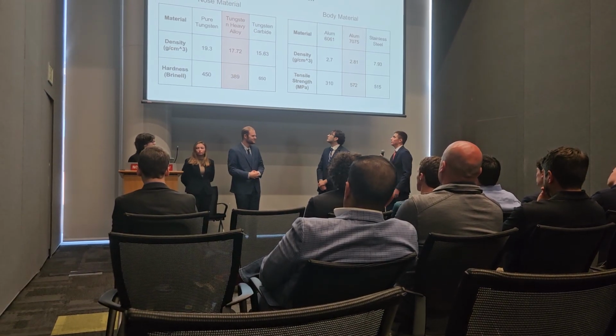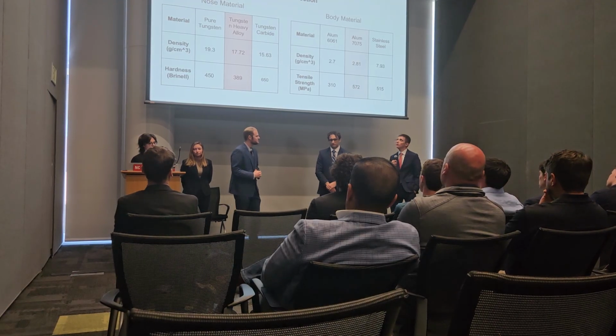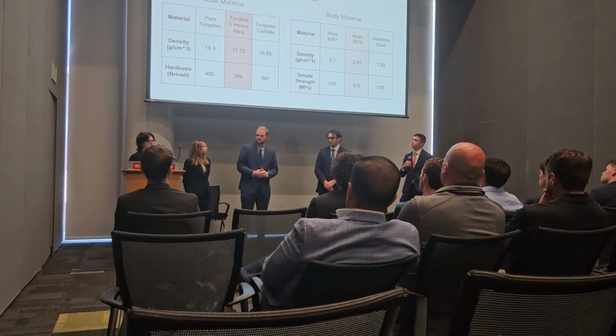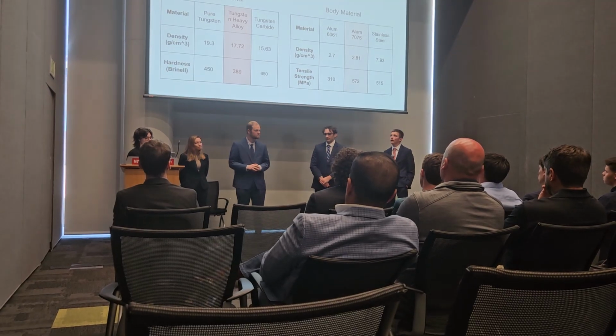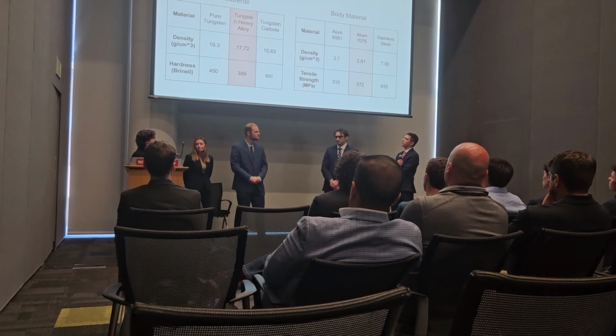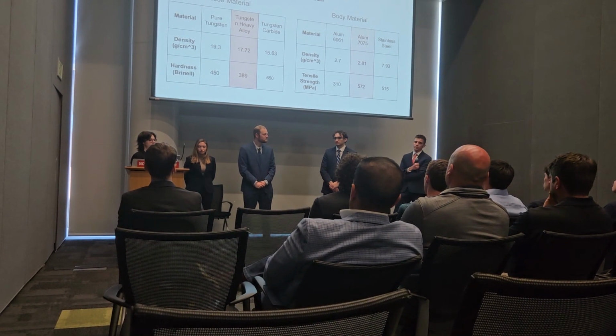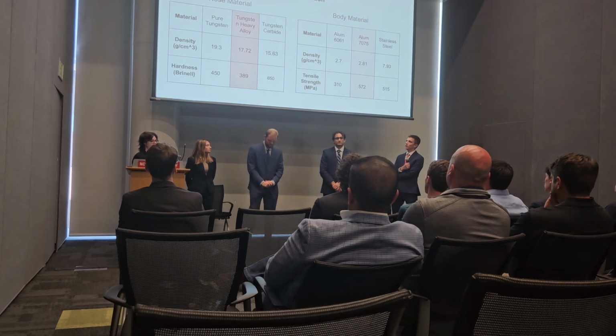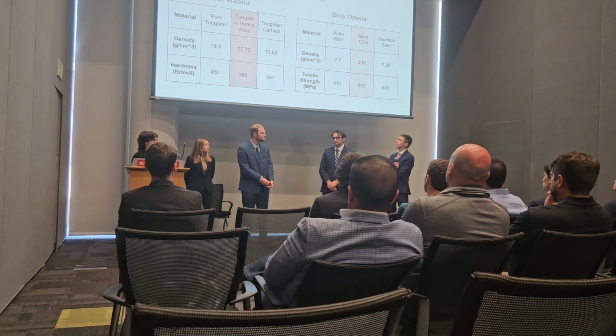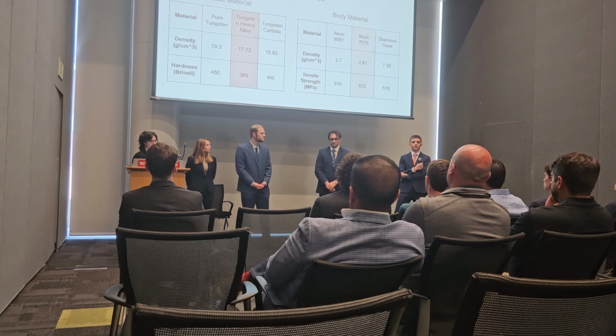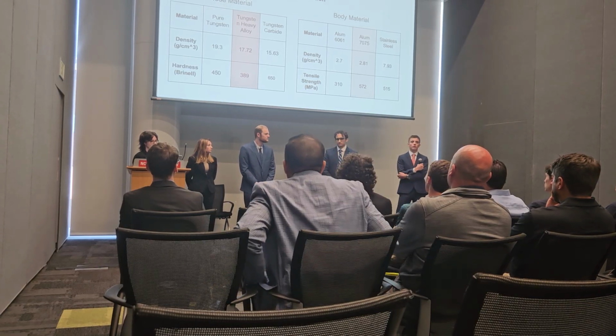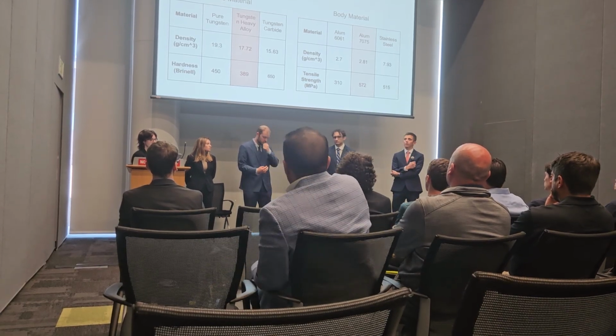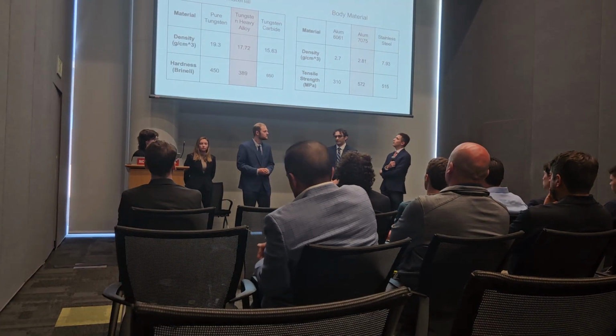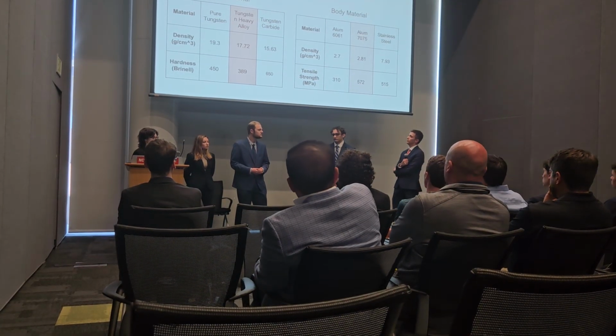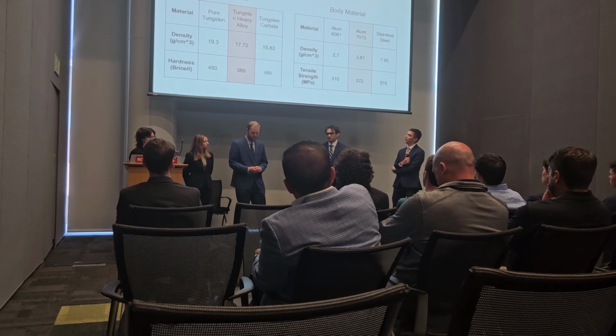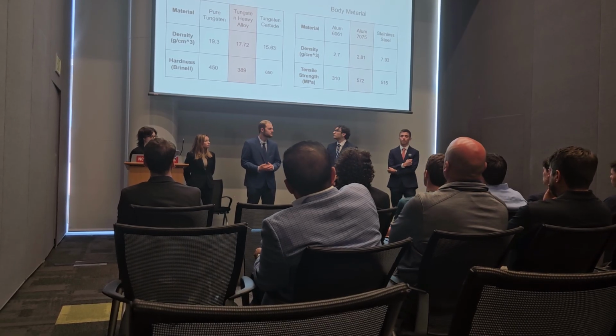So now moving on to our materials, we're first going to start at the nose. We wanted to have something that was strong, something that was dense, that could withstand an impact. So we first started out with pure tungsten, which had a good density and a good strength, but it turned out to be too expensive. So next we went to a tungsten carbide, but like the other group said, it is very difficult to machine. So that left us with the tungsten heavy alloy, which had pretty good properties, with a density of 17.72 grams per centimeter cubed and 389 hardness per Brinell number.